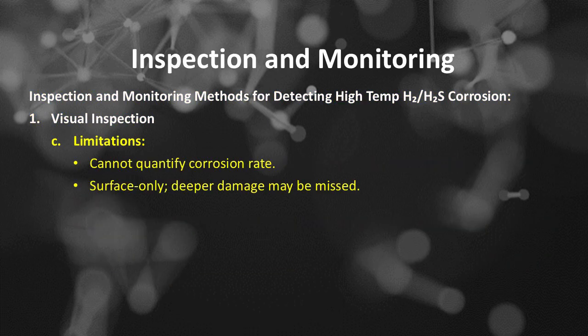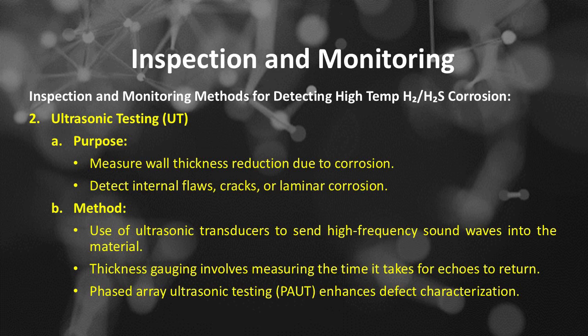The limitations of visual inspection include: cannot quantify corrosion rate, surface only, deeper damage may be missed. Inspection and monitoring methods. Number 2 is ultrasonic testing, or UT. This is purposed to measure wall thickness reduction due to corrosion, and also to detect internal flaws, cracks, or laminar corrosion. The methods of ultrasonic testing include use of ultrasonic transducers to send high-frequency sound waves into the material. Thickness gauging involves measuring the time it takes for echoes to return.